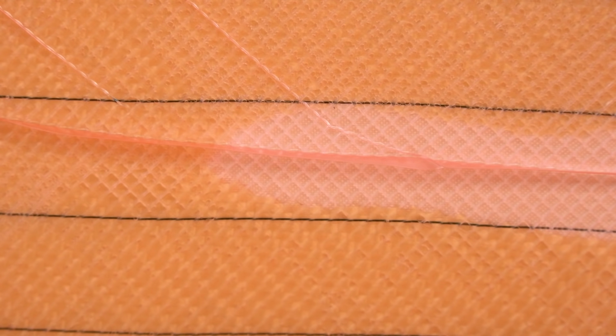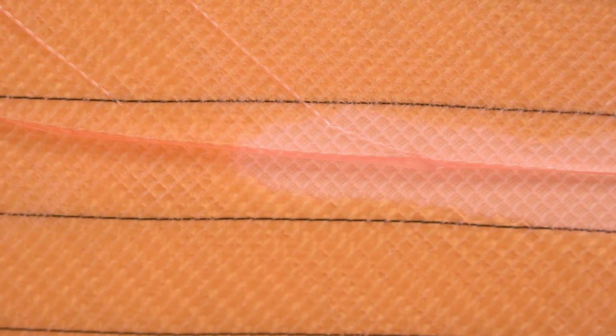Although this should never happen if you've done a thorough drop test, if you do see a stream of bubbles emanating from one point in the bag, it is possible to plug the leak with some sealant tape as the part is infusing. It is worth noting it's not always easy to track down the source of the leak, and this should never be relied on as a method of fixing a leak that you knew was there before starting.